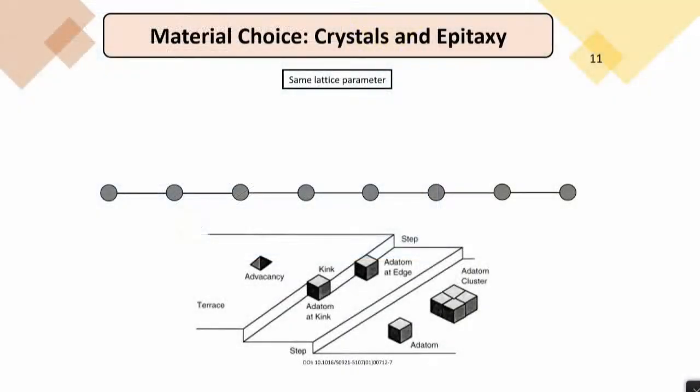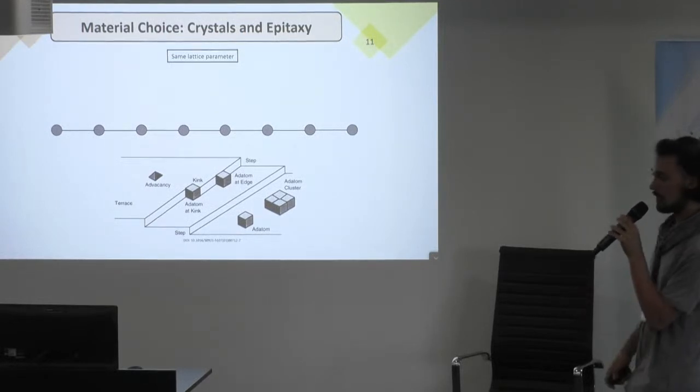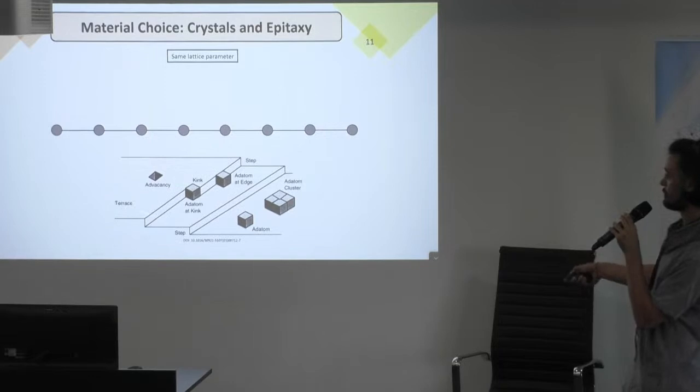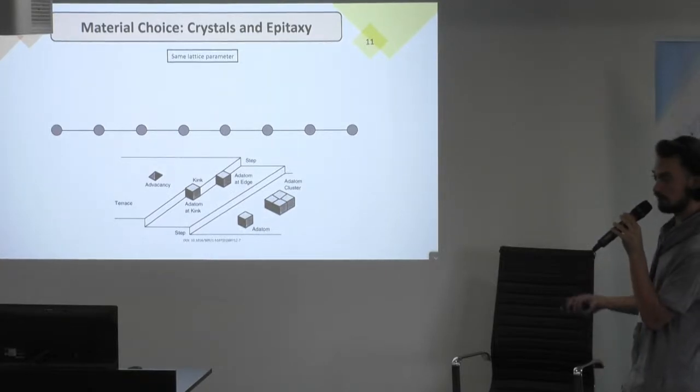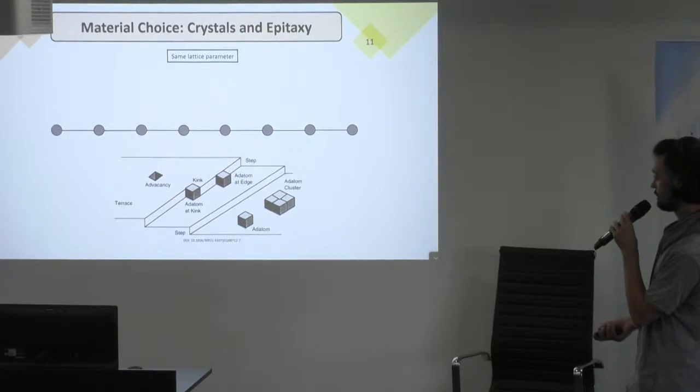So now I'm going to show a bit how an epitaxial growth would happen, and this is a very famous image for crystal growers. Imagine we have this kind of structure with some steps, and we have some atoms that get to this surface. This atom here would close one bond with the surface, but would leave 5 more free. So this is not energetically favorable.